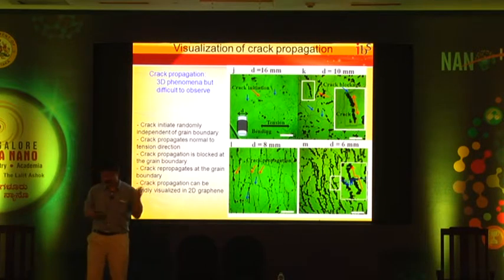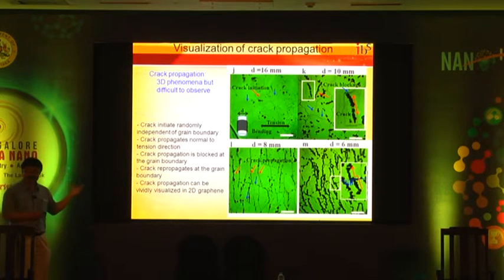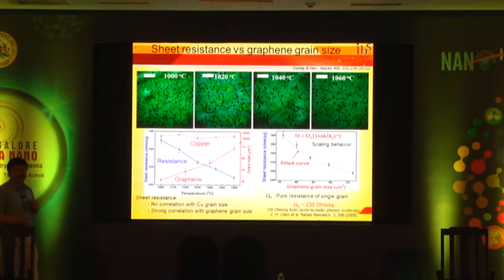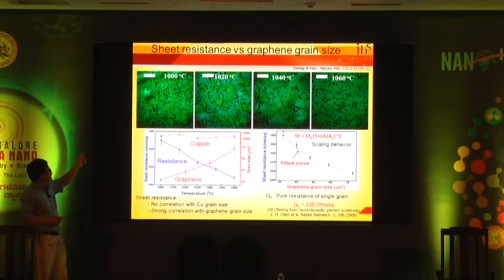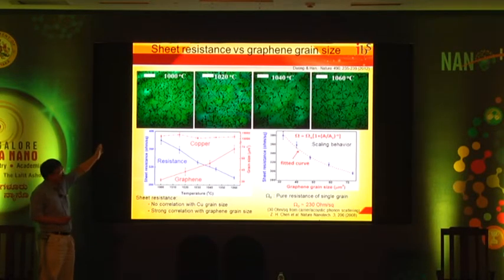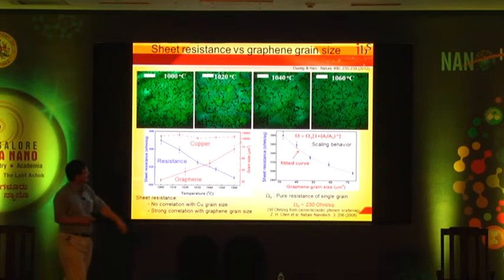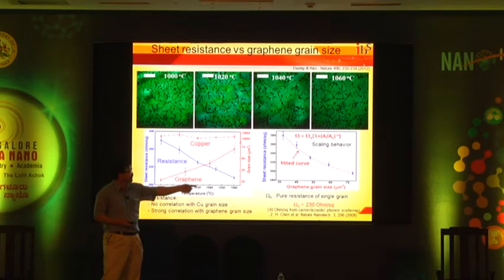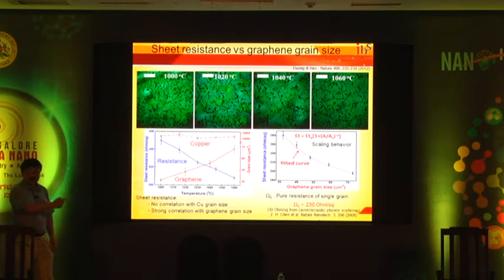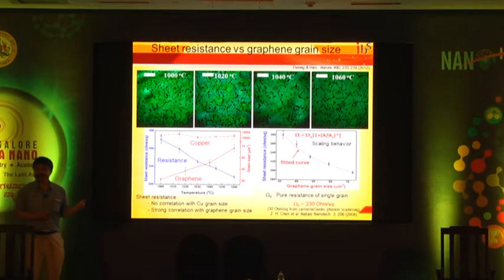A three-dimensional case is not easy to observe, but just a simple tool that we invented allows us to observe these kinds of things. Another thing that we are interested in, of course, is electrical property. By simply changing the growth temperature of this polycrystalline graphene, by increasing temperature, we can increase the size of the grain and reduce the grain boundary. Combining all this, here is a summary. Sheet resistance versus graphene grain size: the sheet resistance decreases with increasing grain size, which follows this simple scaling behavior. The pure resistance of the single grain is 230, which is still large because CVD-grown graphene still has point defects in the grain, even without the grain boundaries.